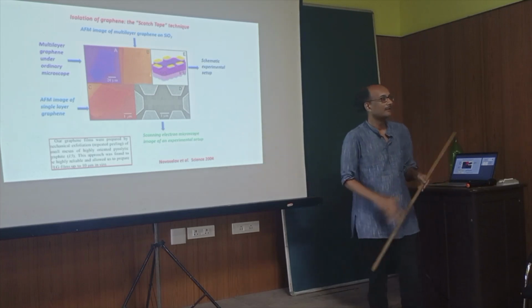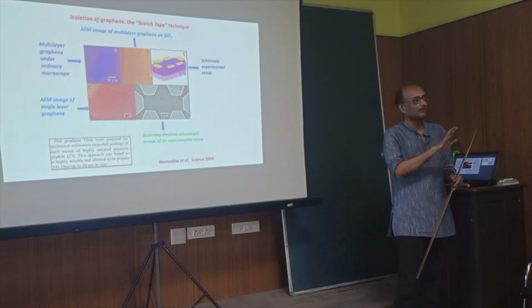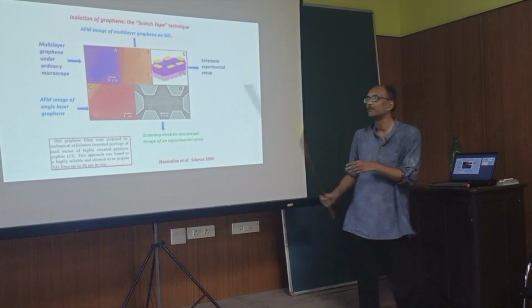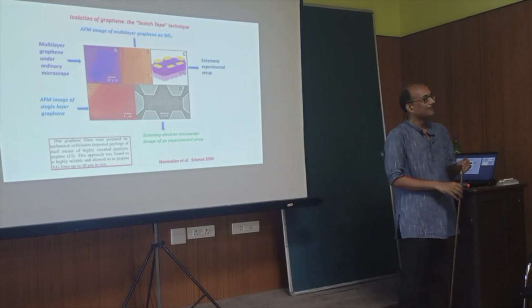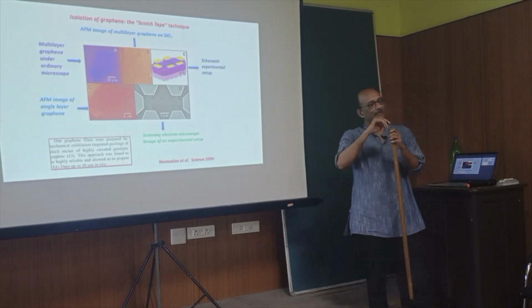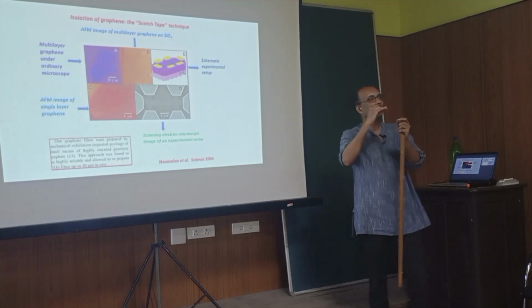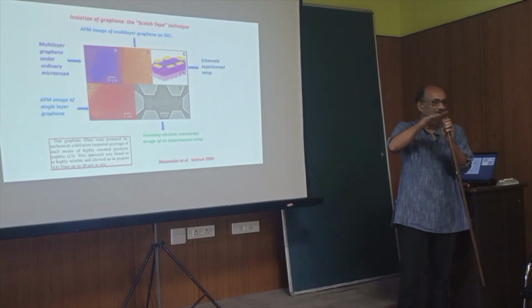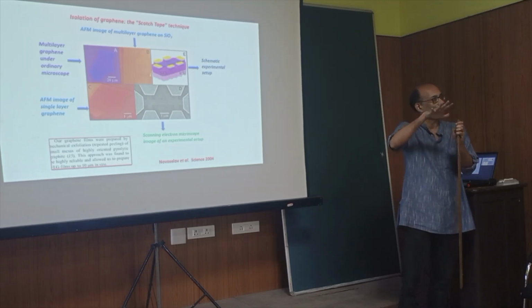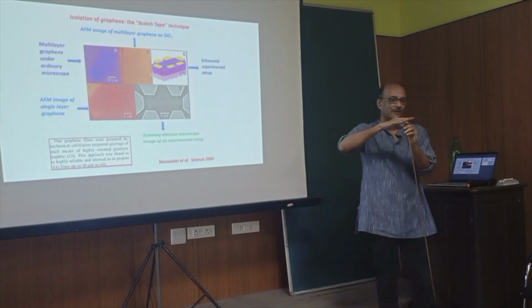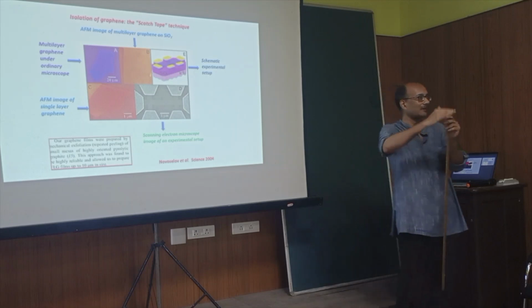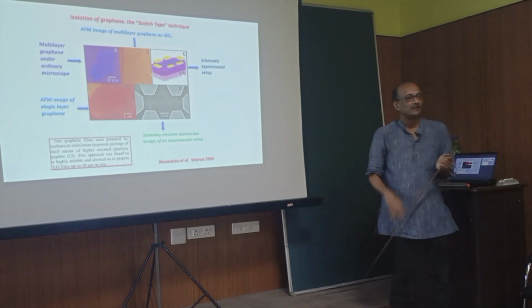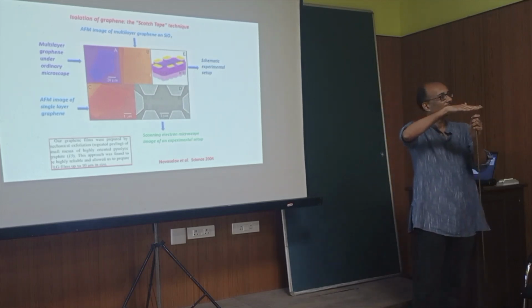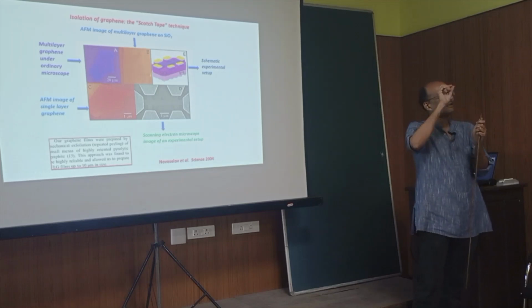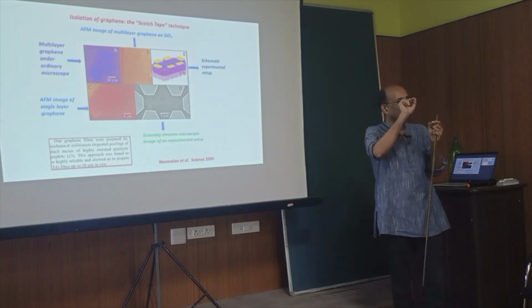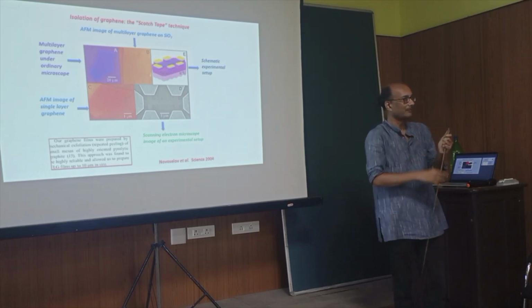He suddenly realized that the student was absolutely correct. You cannot really get a few layers of graphite this way. But he came up with a very interesting solution. Just before you do the cleaving, you polish the surface of graphite with some scotch tape, so that it's really shiny, and then you cleave. He realized that while polishing the surface with scotch tape, little flakes of carbon get absorbed into the tape.